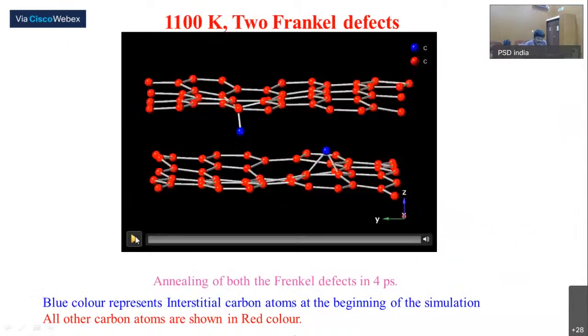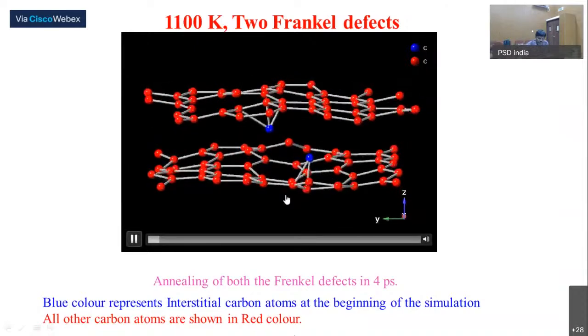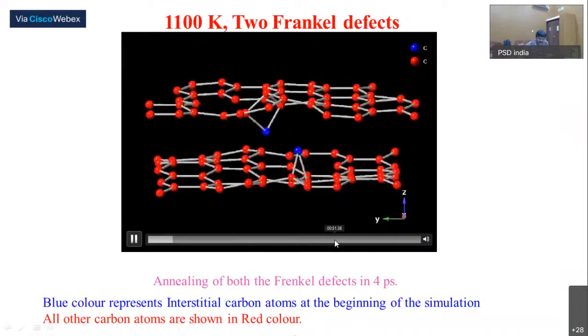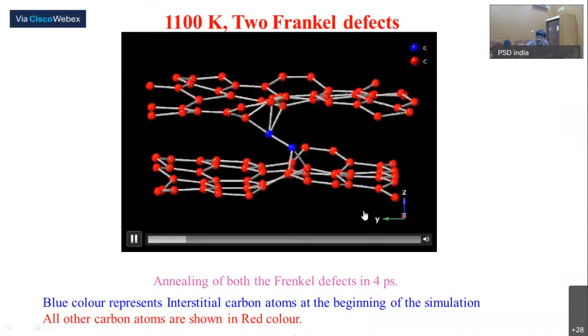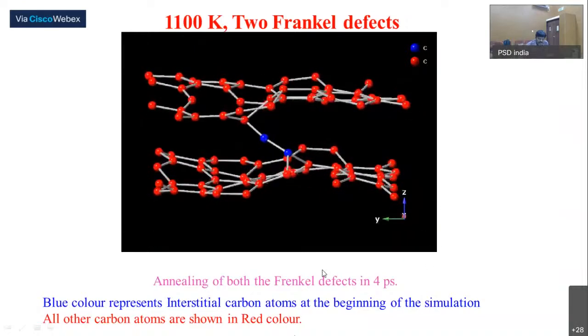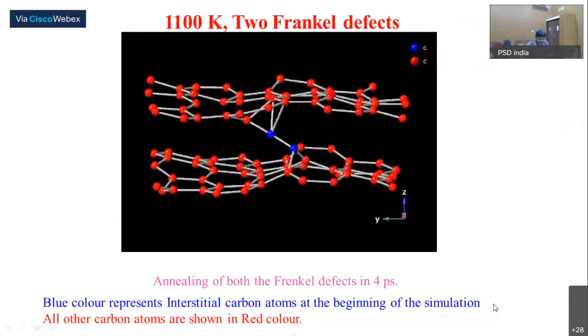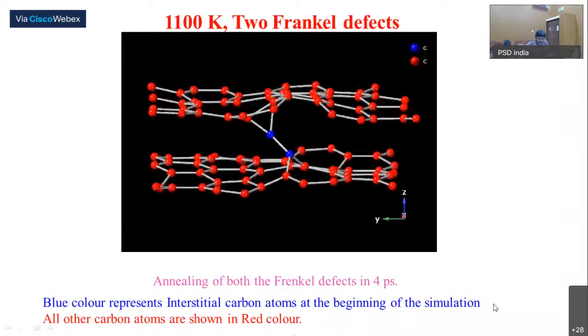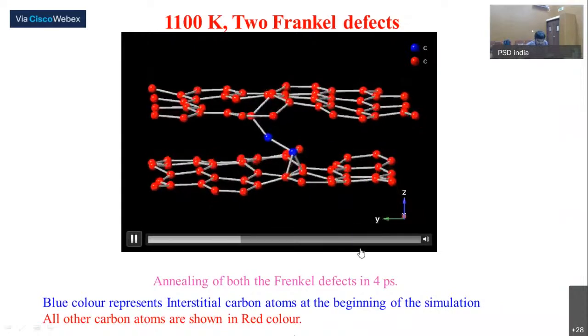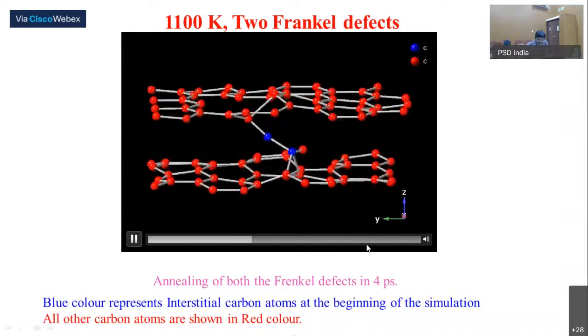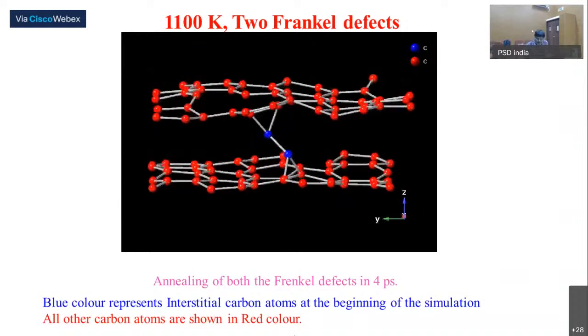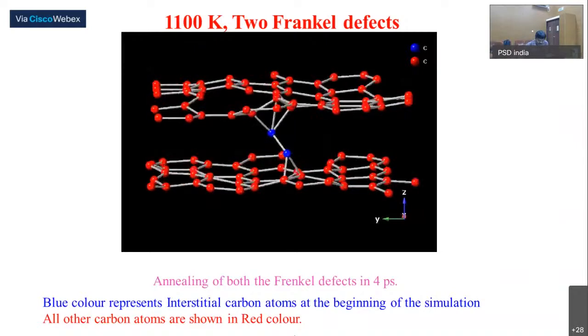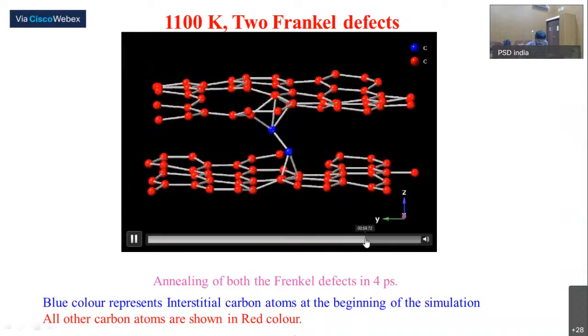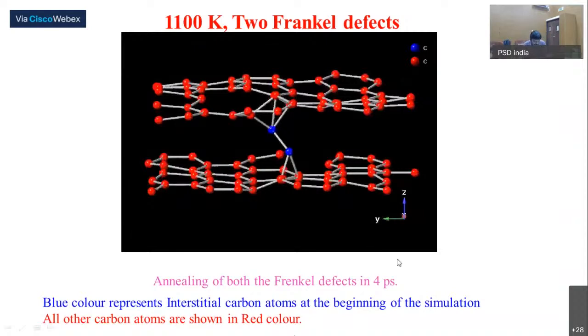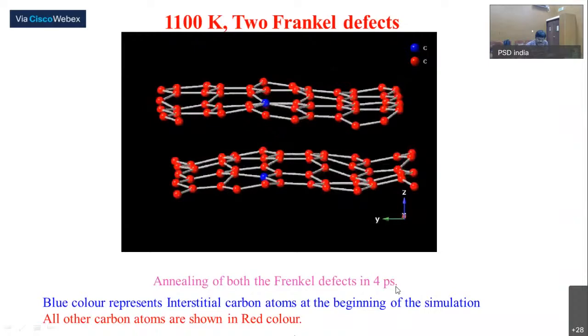And this is the movie with 2 Frenkel defects, and we find that after 4 picosecond both these layers would have 6 member rings. Now this has become fully 6.